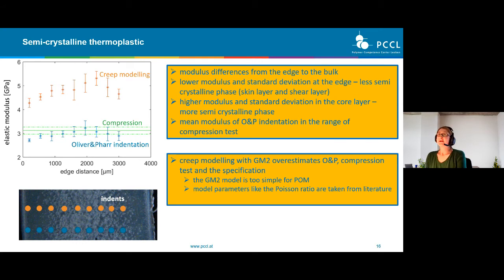Now I did nanoindentation measurements over the sample of POM, so over the cross section, which you can see down here. So I have indents in this region where we have less semicrystallinity, and when I'm going deeper into the material, we have higher semicrystallinity. And when I do nanoindentation, you can see here in blue the Oliver and Pharr indentation, and in orange the creep modeling indentation. You can see that for both measurements, we have a lower elastic modulus at the edge of the sample and a higher elastic modulus in the center of the sample.